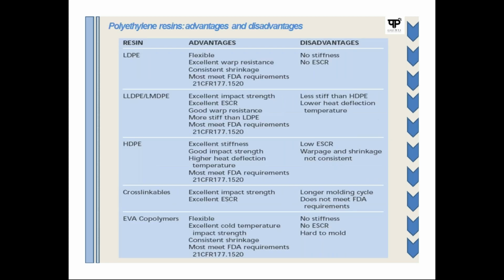Now in this case, if we are using this particular material, what are the advantages? As I said, LDPE is a low strength material, so it doesn't have good stiffness and doesn't have a very good ESCR, environmental stress cracking resistance. But if we use LLDPE or MDPE material, medium density polyethylene, there the stiffness is less compared to HDPE, but more compared to LDPE material. And there is a lower heat deflection temperature. This is one of the disadvantages.